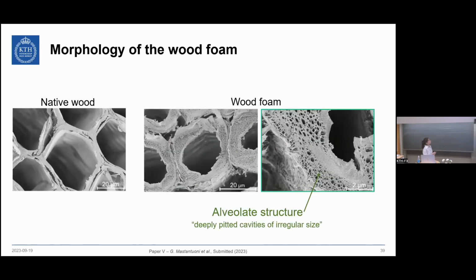And here we can compare the structure of native wood, with a quite thin and very compact cell wall, to the obtained wood foams. Here we see that the cell wall is much thicker, and we have a lot of porosity, which we define as alveolate structure. So it's an array of deeply pitted cavities of irregular size.